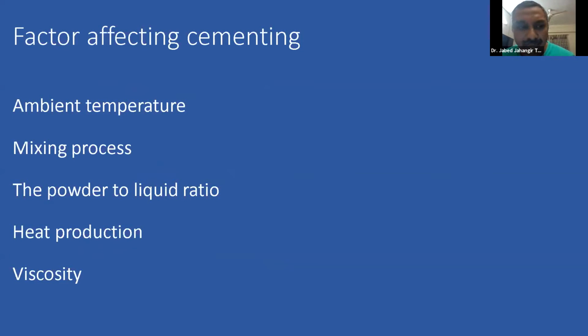Few factors are more important: the ambient temperature, mixing process, the powder to liquid ratio, heat production, and viscosity. I will just talk about ambient temperature and viscosity. If you want to keep bone cement in a refrigerator, keep it half an hour before. But before cementing, you should remove it about 5 to 10 minutes before, and bring it to your operating room temperature, which should be kept around 21 degrees centigrade. And mixing process, if you mix vigorously, then heat production is much more and polymerization will be rapid. So your working time will be short. So you should be gentle. And there should be a proportionate powder and liquid. If one is more, you can face problems with the setting and working time.